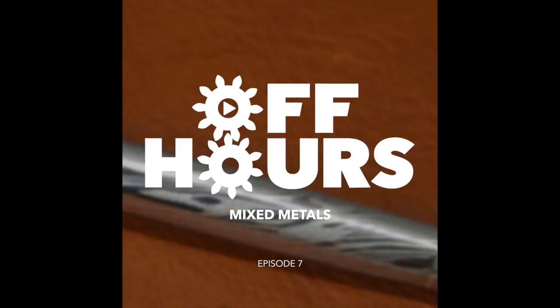So one of them might be a lower carbon steel where it's more flexible and can handle shock better, but it's not as hard, so it doesn't get sharp. And then the other steel will be a higher carbon steel, so it can hold an edge, but it's more brittle and therefore doesn't take shock very well. So you get the advantages of both the sharper, harder metal and the softer, shock-resistant metal sort of melded into one piece.